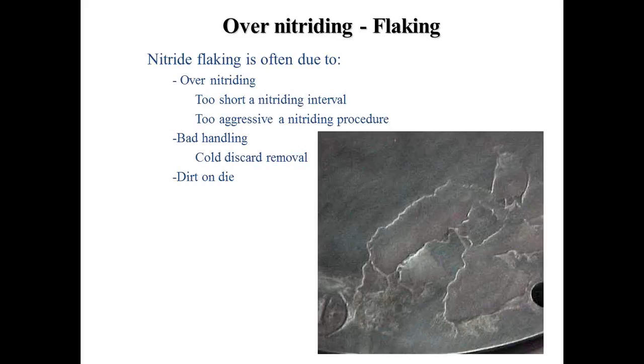Now you may look at this and say, hey, this is a piece of die steel away from the bearing, why am I worried if it's flaking? Well, I can assure you if one of those pieces of flakes gets pulled off the surface during extrusion and ends up going through the die, you will notice this in your product and it may actually have a permanent effect on the bearing. So it's good to avoid.